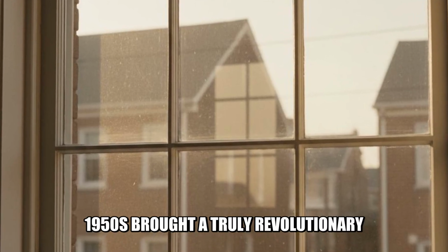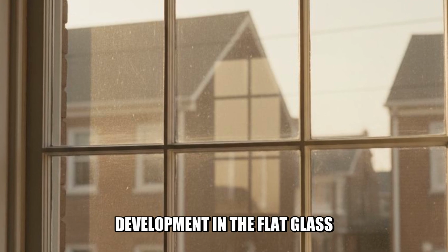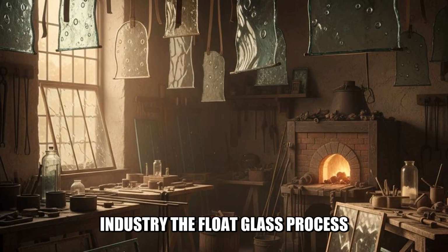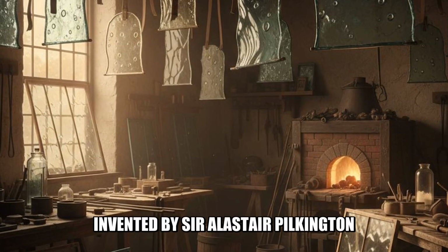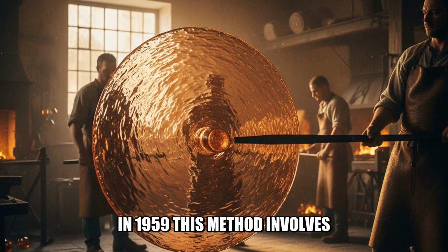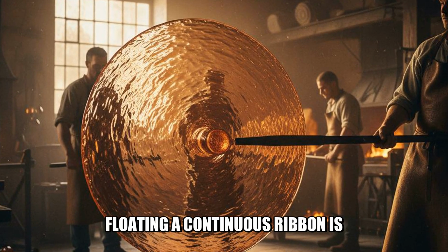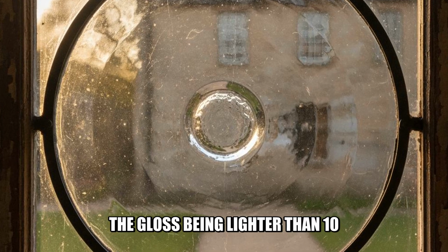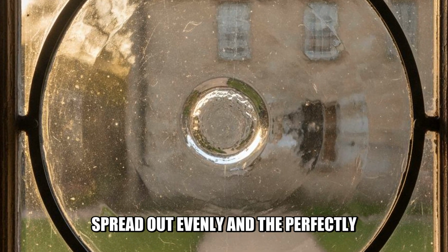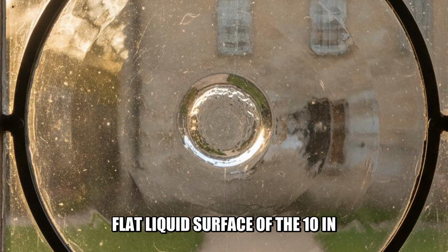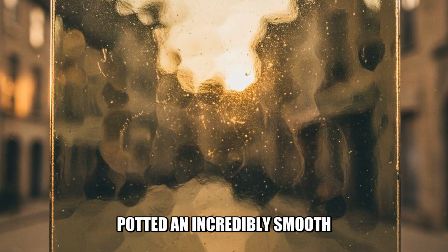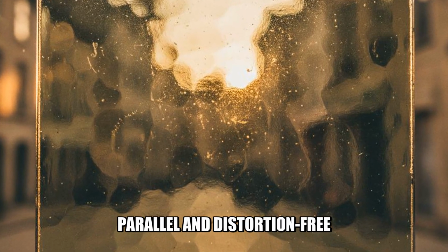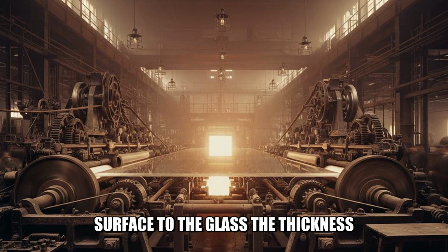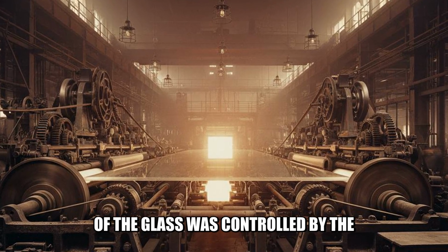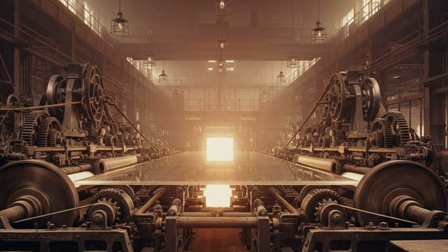The late 1950s brought a truly revolutionary development in the flat glass industry, the float glass process, invented by Sir Alastair Pilkington in 1959. This method involved floating a continuous ribbon of molten glass over a bath of molten tin. The glass, being lighter than tin, spread out evenly, and the perfectly flat, liquid surface of the tin imparted an incredibly smooth, parallel, and distortion-free surface to the glass. The thickness of the glass was controlled by the speed at which it was pulled from the tin bath.